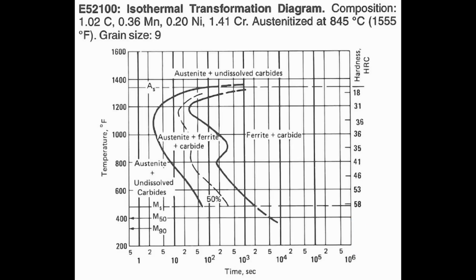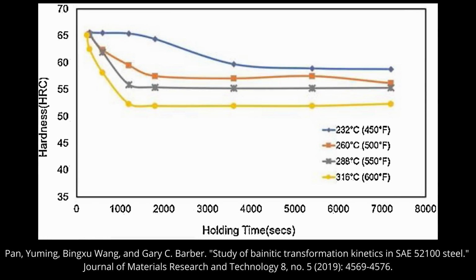Now, sometimes it can be difficult to find TTT diagrams for every steel, but you can also make your own transformation measurements. What you can do is austemper for different lengths of time and then find where the hardness levels off. Here is a diagram showing experiments from a journal article on 52100 where they austempered at different temperatures: 450, 500, 550, 600 degrees Fahrenheit. When they held the steel at the temperature for a very brief period of time and then quenched, it's almost all martensite.